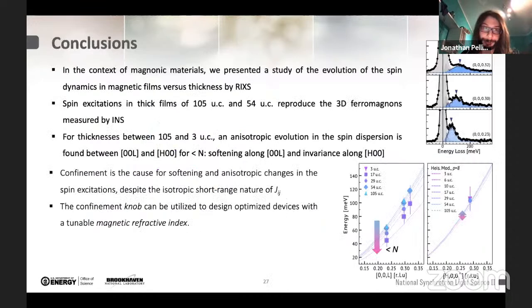Now, I will conclude this section of my talk by presenting our conclusions. I presented an investigation of the evolution of the spin excitation in a magnetic thin film using RIXS. And I want to state once more that it is pretty remarkable that RIXS is able to investigate materials that are extremely thin, as thin as 3 unit cells in this case, and still get reasonable results in a reasonable amount of time. And this opens a completely new research line, which is the investigation of thin films using this pretty advanced spectroscopy.